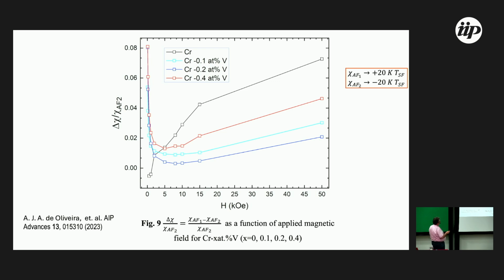My speculation is that the size of the jump depends on the cooling down magnetic field, 50 kilo-Oersted here. The magnetic moment due to the local spin density wave in 0.4 is equivalent to 5 Tesla inside the sample, because we observe this same jump. Okay? When you decrease the field, it is more intense here, because the jump of the spin flip is associated with the single Q state produced by the impurities. Okay?